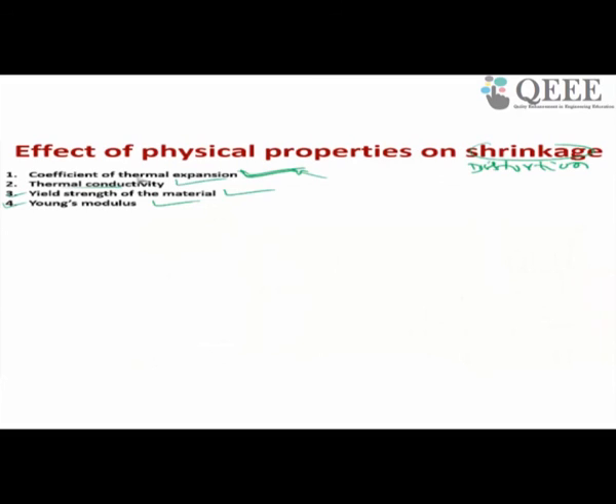So if you take aluminum to steel, aluminum, what about thermal conductivity? So we have four parameters. What are the four? Coefficient of thermal expansion, thermal conductivity, yield strength, Young's modulus. Okay. So now let us take aluminum to steel. Aluminum has very high coefficient of thermal expansion, 13.2, and steel has around 6.7. So aluminum has 2 times coefficient of thermal expansion, 2 times CTE.